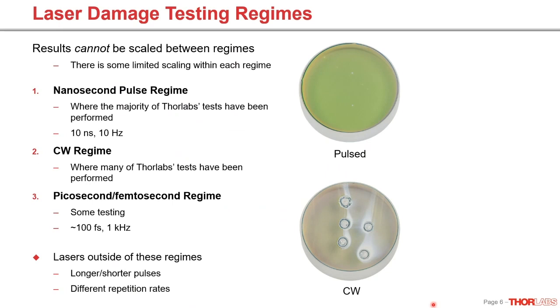The most important takeaway I would say here is that results cannot be scaled between regimes. Just because you have, say, a nanosecond damage threshold, that is not going to govern how the part is going to behave in either the CW regime or in the femtosecond regime. So just please bear that in mind.